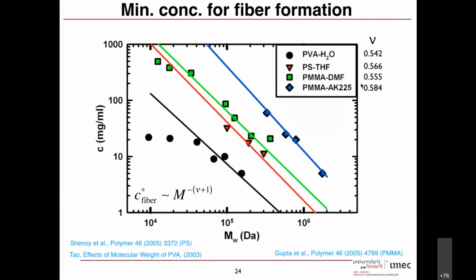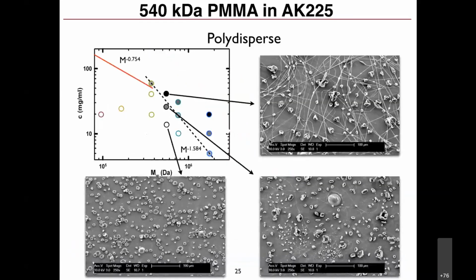Now if you take all these lines, you pick the molecular weight, you pick your solvent quality plus one, and you get these lines. So the theory and experiments seem to match. Then you can go back to my experiment. This is 540, some other molecular weight I took, and this is how the curve looks. This is the slope that I'm getting, molecular weight to the power of 1.58. So I'm able to define it nicely.